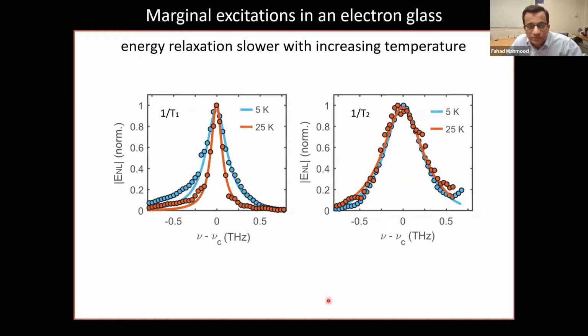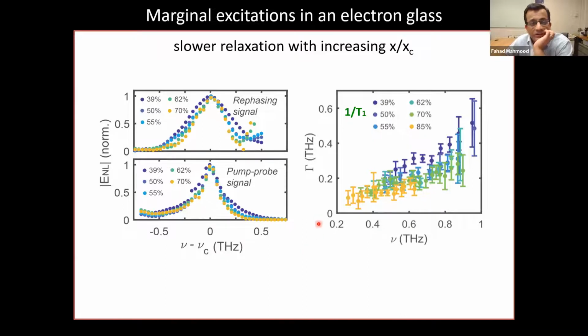And the other interesting thing is what happens as you're increasing temperature. As you're increasing temperature, particularly for the relaxation, the peaks are getting sharper, okay? Which is counterintuitive. Usually when you think about pump probe traces or relaxation with temperature, things get faster rather than slowing down. So this behavior is inconsistent with phonon behavior. Okay. What we think is happening is this temperature dependence is actually more consistent with the presence of electron-electron interactions or some quasi-particle interactions, because as you're increasing temperature, you may be going above this mobility edge or making excitations in the conduction band, and you're decreasing screening, and maybe that is suppressing our tunneling in some sense. So maybe that's an overview, but we still need to understand this a little bit better. But the key point is, even with other dopings, the scattering rate remains linear with frequency.